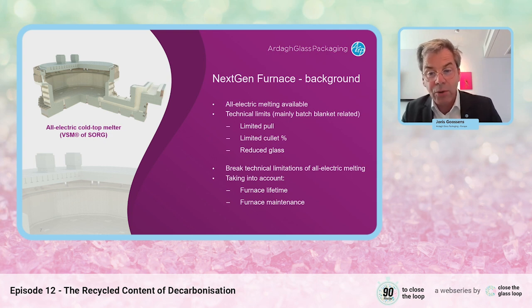It has to be intact at all times. And because of this limitation, the pull of this furnace is limited to 200 tons per day max. It depends on the color and depends on the type of glass, but let's say 200 tons max. And also the amount of cullet which can be used in this type of furnace is limited to around about 50%. And this type of furnace cannot produce all glass colors. It can only produce oxidized glass colors, which means the lighter greens, the blues and flint glass, but not amber and not the darker greens.